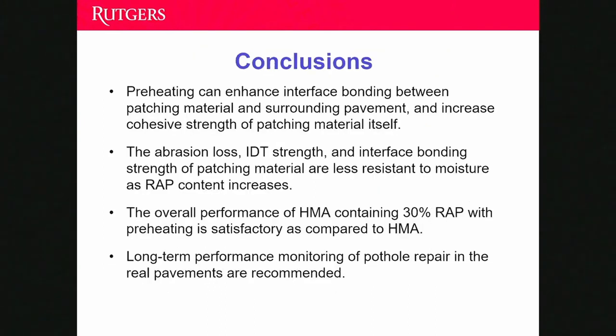And here are the conclusions of this study. From both the laboratory and the field evaluation in this study, again, we verified the positive effect of the preheating, and we found that the preheating can not only enhance the interface bonding condition, but also the cohesive strength of the patching material itself. And although the abrasion loss, IDT strength, and the interface bonding of the patching material were less resistant to moisture as the RAP content increased, after adding 30% wrap, the overall performance is still satisfactory as compared to HMA. This actually verifies the feasibility of using the combination of RAP material and the preheating in